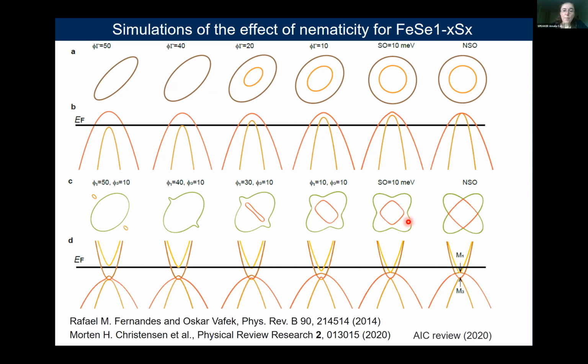But in the presence of spin-orbit coupling, this degeneracy is lifted, and then turning on the nematicity, we can see how these pockets start distorting, squeezing the inner electron band, as you can see, as this dispersion is touching the Fermi level. And eventually, if these effects are pushed further and further, some topological changes could occur for the electron bands, and this can disappear altogether, and two little pockets could be left for very, very strong nematic effects. So these are the qualitative trends that we could expect in experiments, and we look at the system